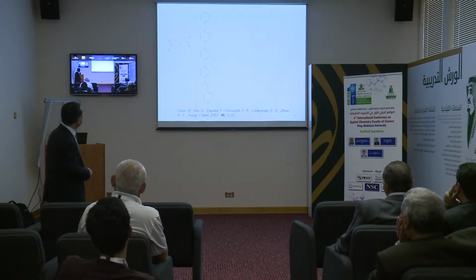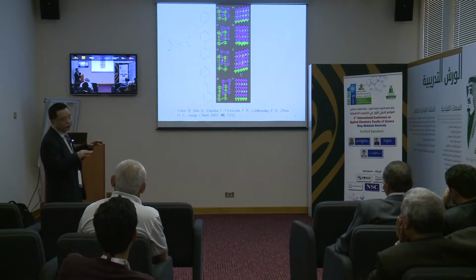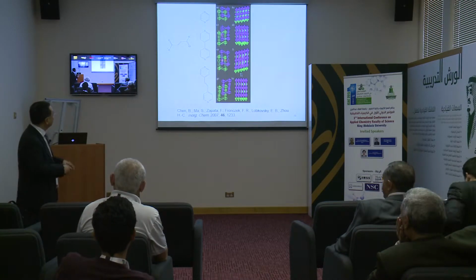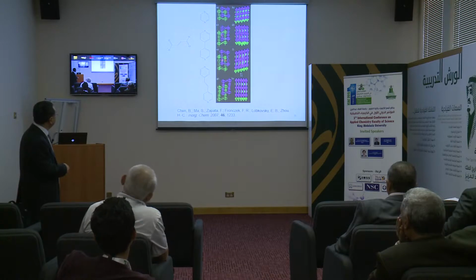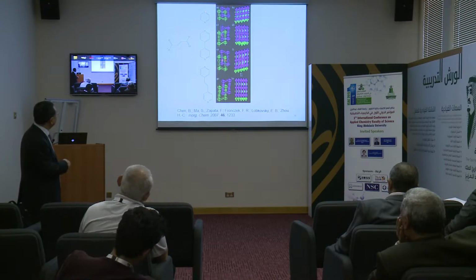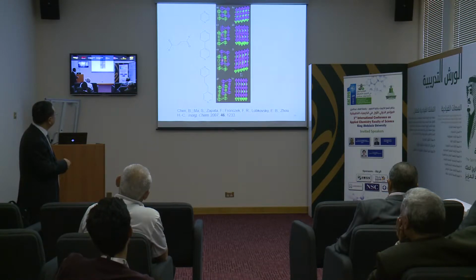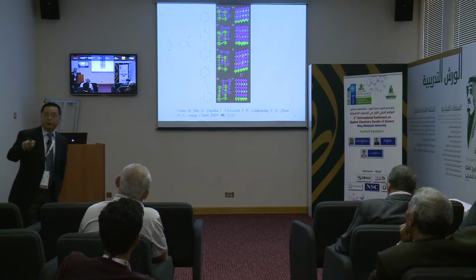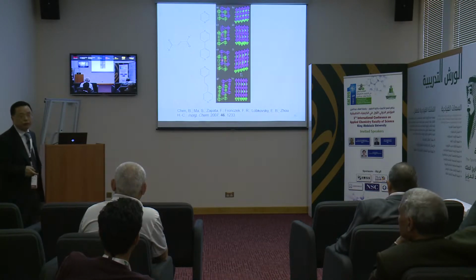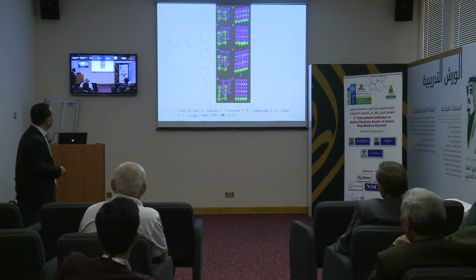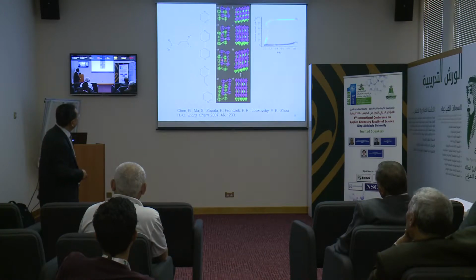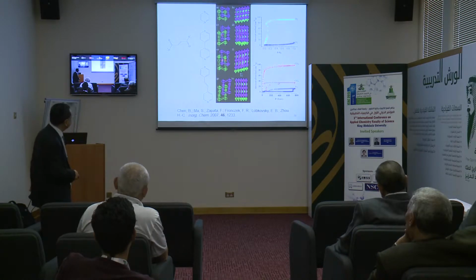With copper, we first form a two-dimensional sheet, and these two-dimensional sheets are pillared by different organic linkers. You will see that with pyrazine, this is a condensed structure, and then the pore is slightly increased, and this one, a little bit larger, is about 3.8, I think. So this is suitable to allow hydrogen to go through the channel, where methane and nitrogen sometimes will be blocked. So it can also be utilized for carbon dioxide capture and separation.